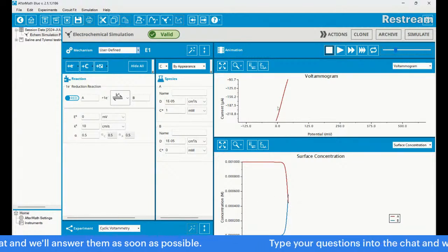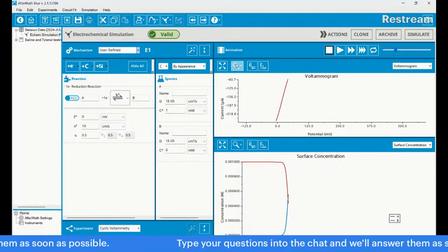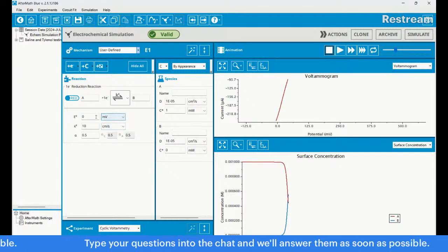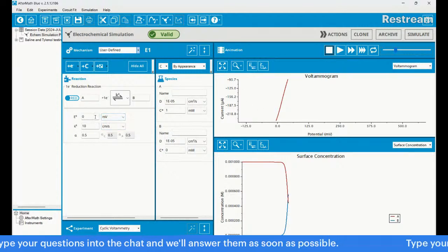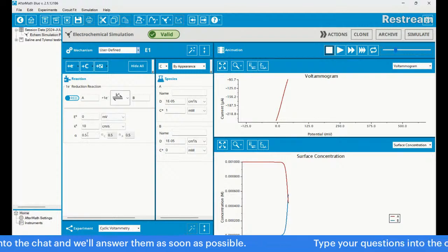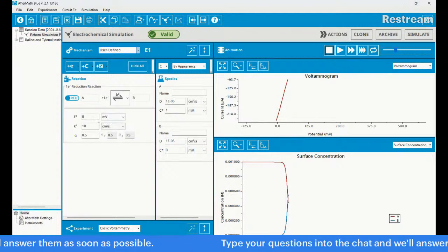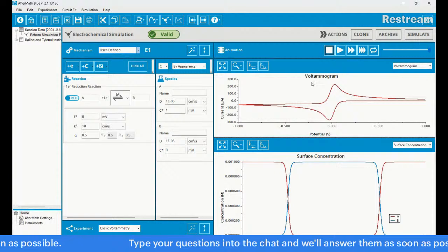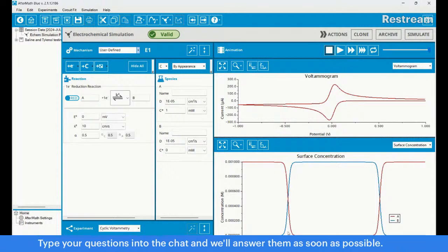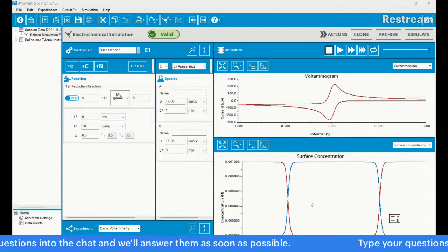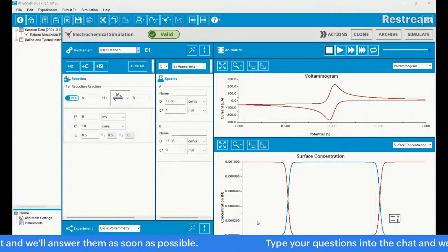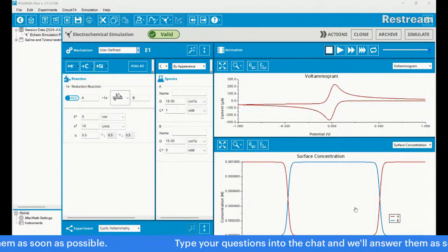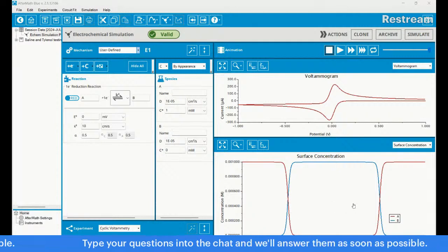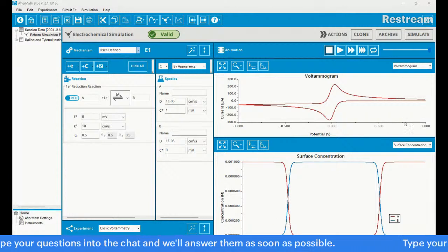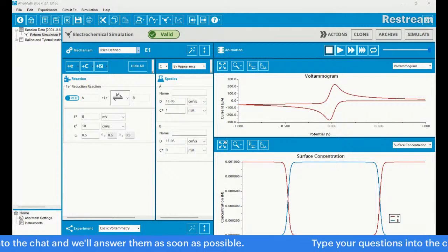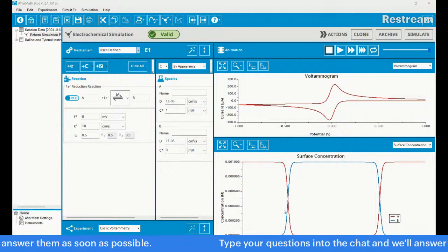it has reached the peak potential. And so it's not the reduction peak or the oxidation peak potential. It's kind of halfway between, or sometimes 70% either way, depending if your electron transfer kinetics are sufficiently fast. So I hope, Nathan, this kind of answers your question. But yes, that's the relationship in a cyclic voltammogram with the standard redox potentials.